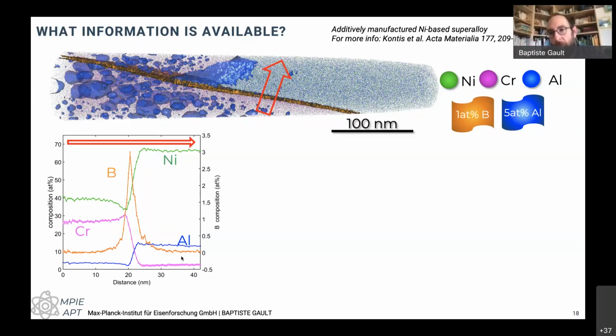And in Ni-Al-Mo, has there been any studies? Because that is a classic case where you can shift the misfit from positive to negative. There's been a lot of work on this like 20, 30 years ago, so not really with the latest versions of the technique, but there's very often moly in these very complex alloys, right? So we sort of know how it behaves in some ways, but within these alloys with 10, 12 elements.